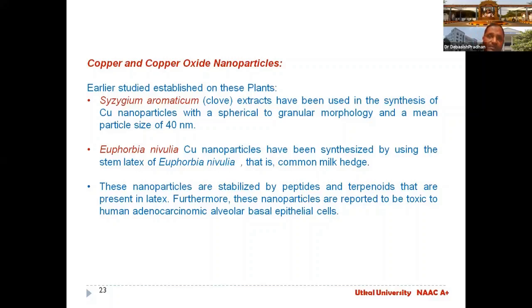Furthermore, the copper nanoparticles have shown potential antibacterial activity against E. coli. The Syzygium aromaticum plant, as I told you, is already established. Its extracts have been used in the synthesis of copper nanoparticles with a spherical to granular morphology and a mean particle size within 40 nm. That is so good. Copper nanoparticles have also been synthesized using the stem latex of Euphorbia nivulia.